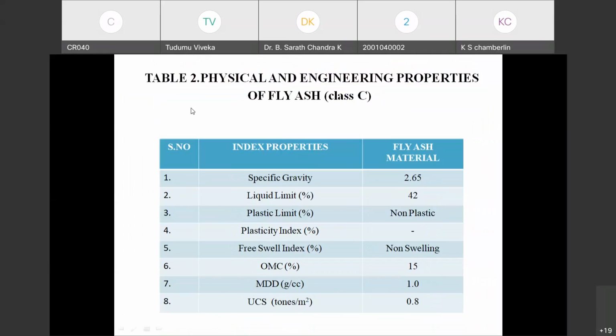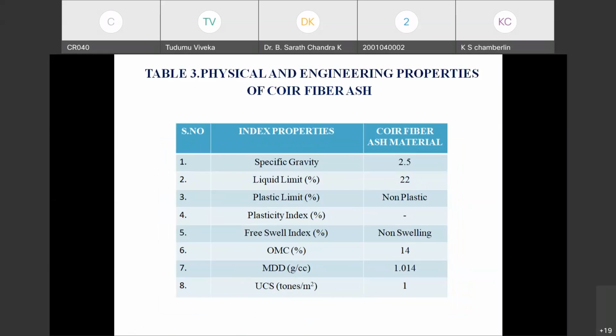And these are the physical and engineering properties of the fly ash. Specific gravity is 2.65, liquid limit 42%, non-plastic, and free swell index is no swelling, OMC is 15%, MDD is 1 gram per cc, UCS is 0.8 tons per meter square. And this is the geotechnical properties of the coir fiber ash. Specific gravity is 2.5, liquid limit is 22%, non-plastic, free swell index is non-swelling, OMC is 14, MDD is 1.014, UCS is 1 ton per meter square.